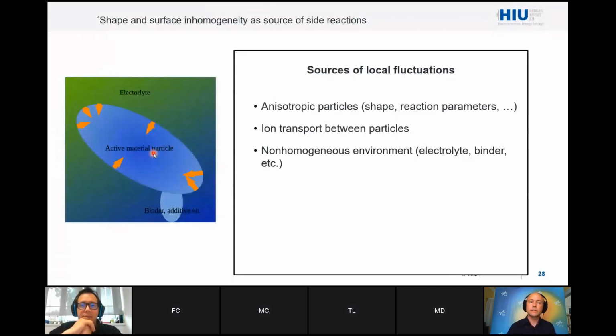And what is most amazing, originally I thought maybe this has to do with some electrolyte concentration gradients, but this is of second order. On first order, 0th order, the same order as the P2D model, we have this curvature contribution or the shape influence. So the statement is, if you do homogenization and you go to the average spherical particle approximation, you lose physics, which is of the same order where you want to get your result on. So the non-homogeneous environment, electrolyte, binder, and so on is crucial.